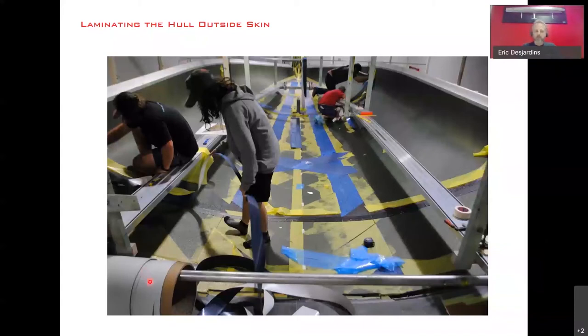You can probably see on this roll it's quite thin. So each layer of carbon is only maybe half a millimeter thin, in some cases 0.3 of a millimeter thin. So again, it's very labor intensive laying all those layers in the correct orientation, one after another. Make sure you don't forget any and make sure you use the right material.